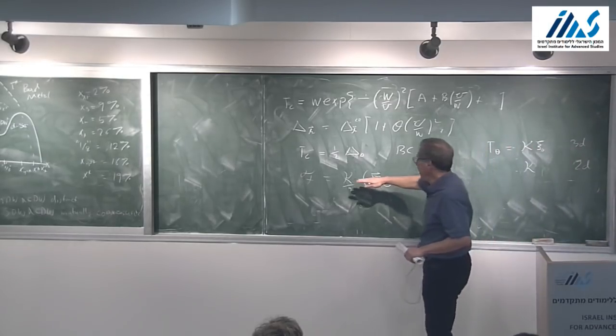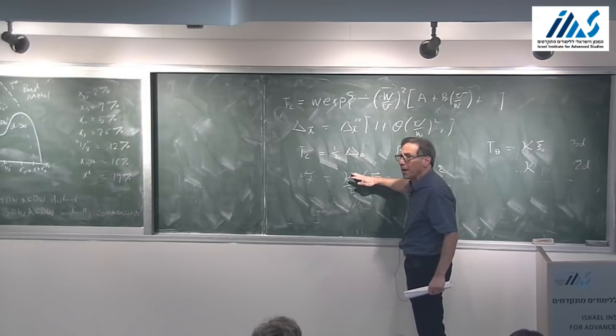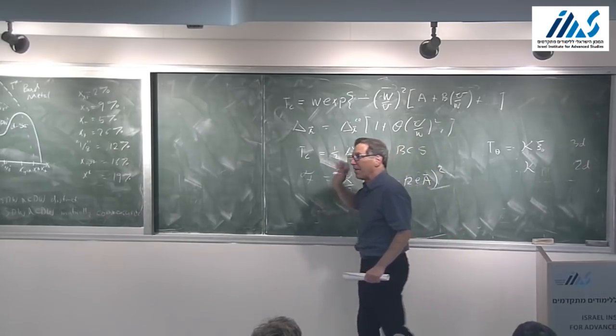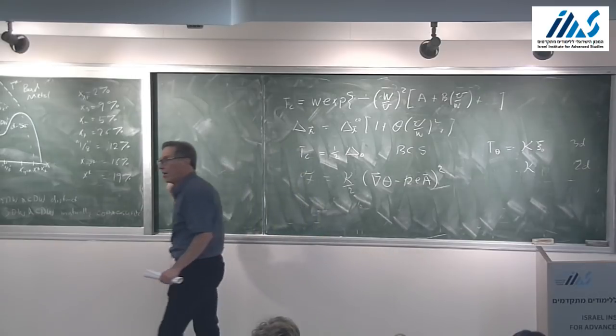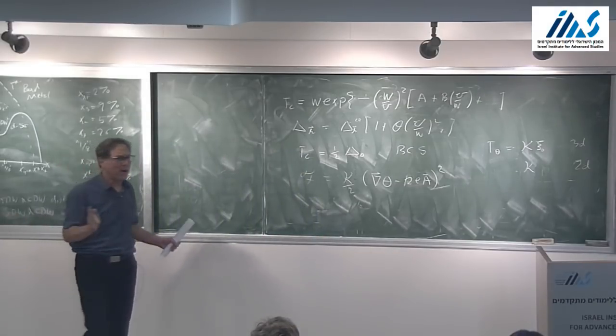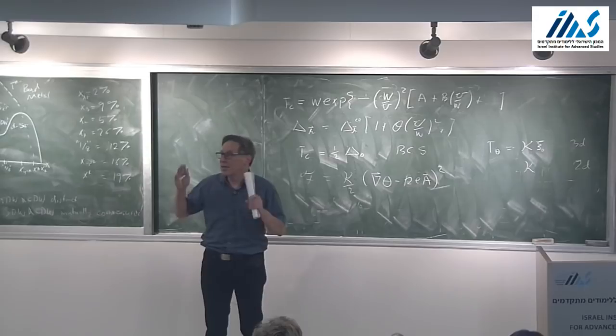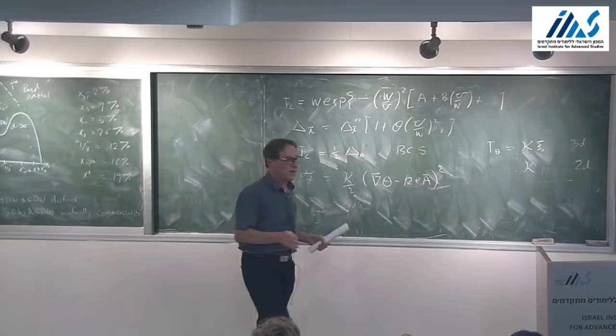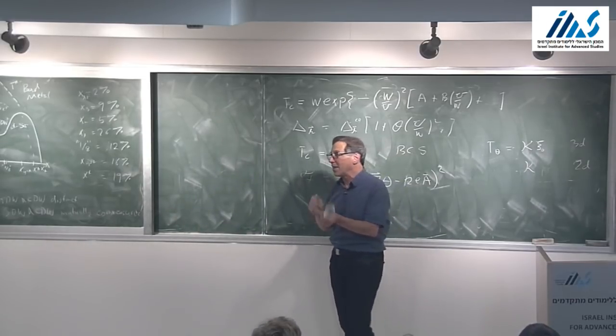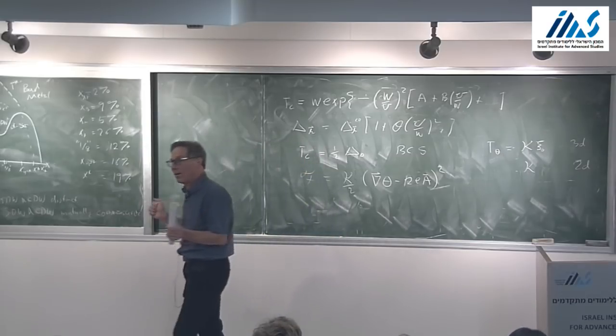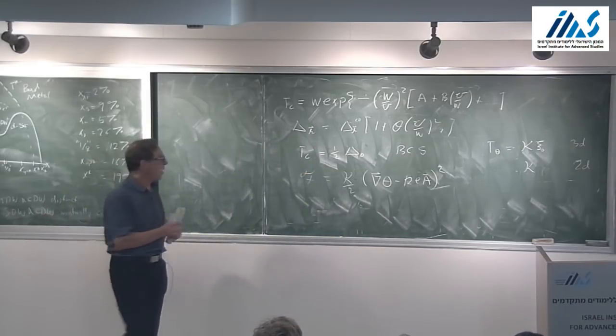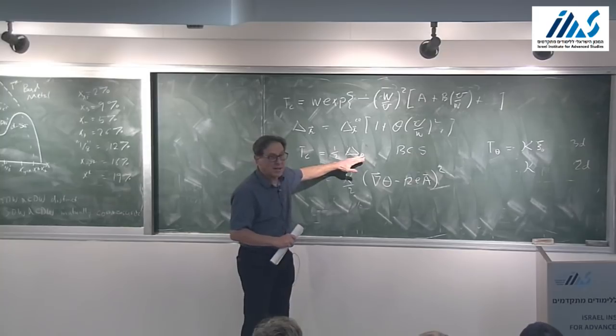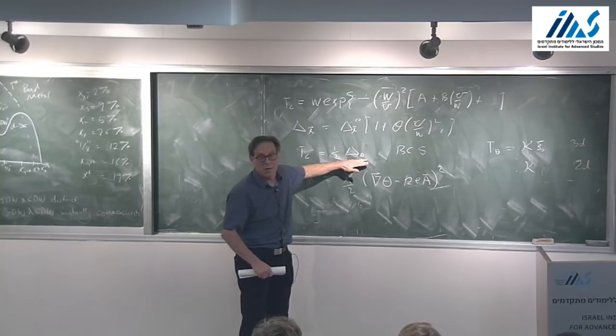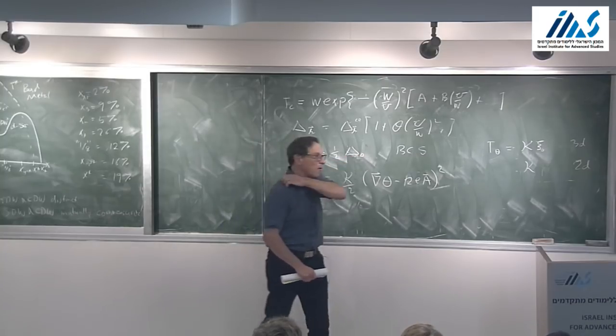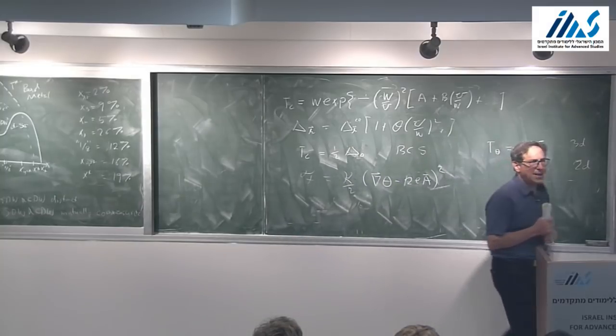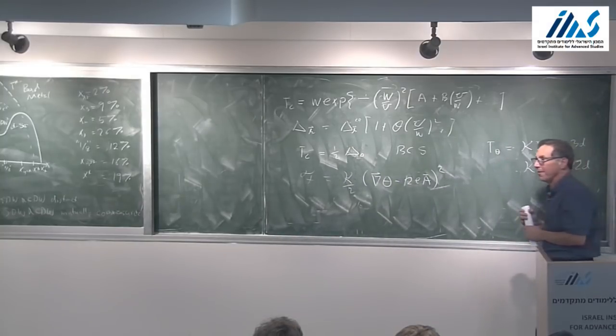Now, typically in clean three-dimensional superconductors, kappa is something on the order of the Fermi energy or bigger. It's enormous compared to Tc, and it's so big that it's totally irrelevant. What that means is that phase fluctuations are extraordinarily stiff. The moment pairs form, they condense, and so the only issue is whether we have pairs or not. And so that's part of the reason for the success of BCS theory.